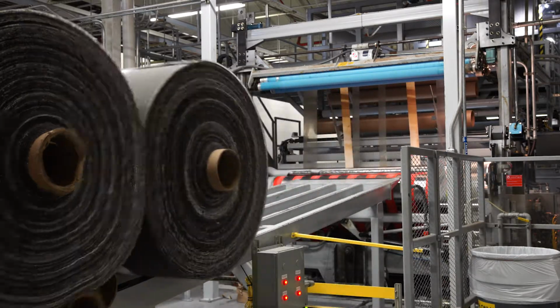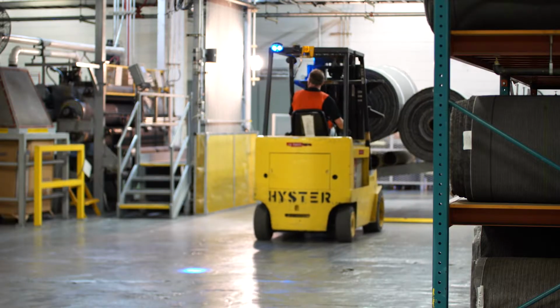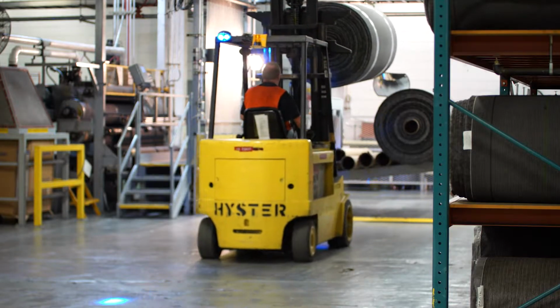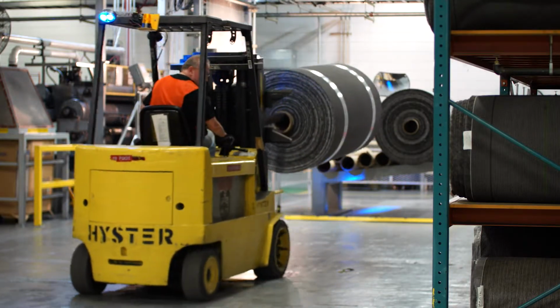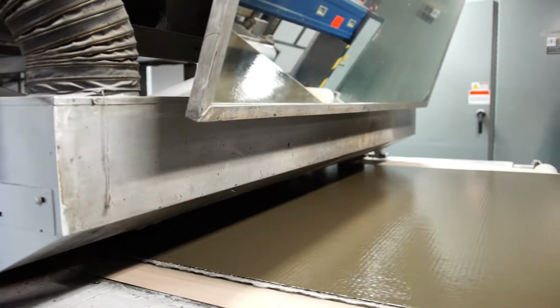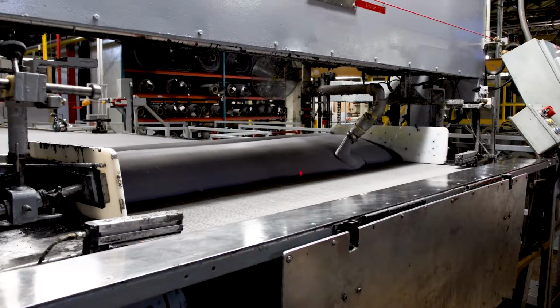A fork truck then picks up the carpet, where it is sent to be backed. Two backing methods are available: the ICT, a PVC-based plastisol backing, and the NXT, a PVC-free extruded backing. The pre-coat that we refer to holds the tufts in place. It does probably 80–85% of the work. The backings finish off the other 15% to hold it in place so that it doesn't come apart